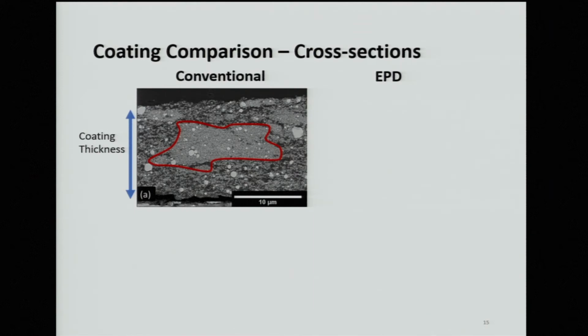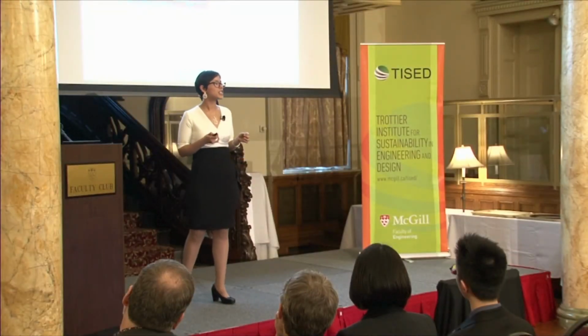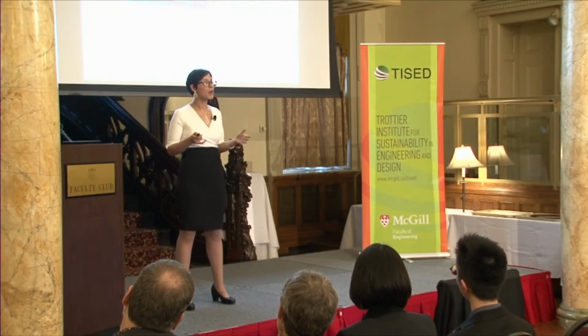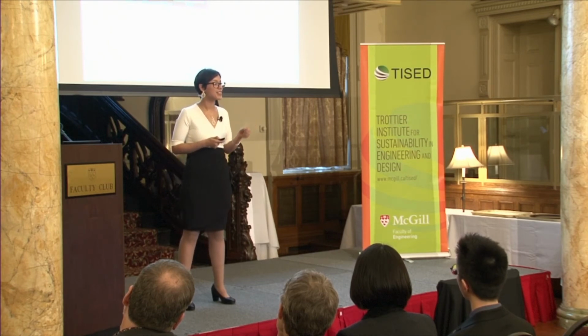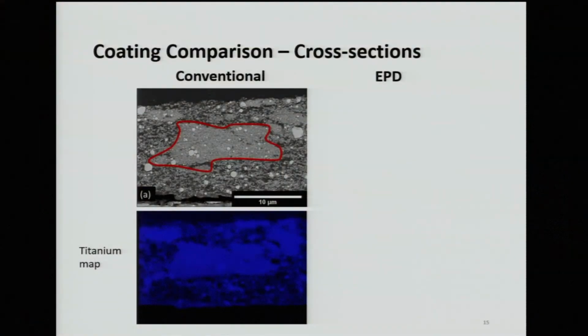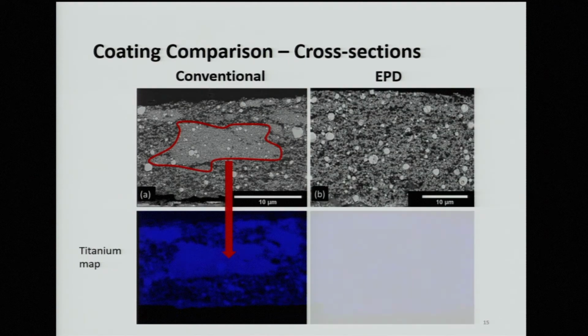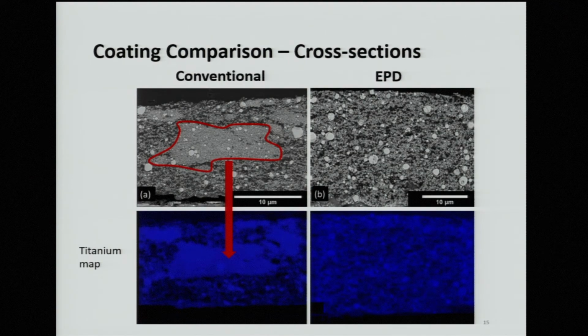With the scanning electron microscope, we can use a technique called energy dispersive spectroscopy, where we can map out elements. Lithium titanate is the only material that has titanium in it. So if we then make a titanium map, we can see where the lithium titanate is spread out. And that's just what we did. So we found out that this gray agglomeration or chunk in the middle is lithium titanate, with the carbon and the binder spread around. Now, if we compare what this looks like with the EPD electrode and its corresponding titanium map, we see a huge difference, right? With EPD, we can say we have a more uniform coating.